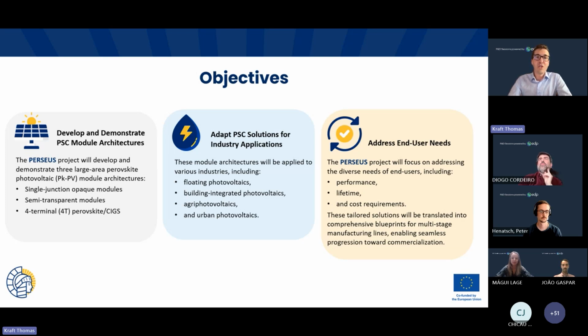One is the single junction opaque module, with a carbon back contact electrode. So basically you're just shining from one side, being illuminated from one side of the PV device. The other is a semi-transparent module in which you can have a bifacial feature, but also the semi-transparency enables this 4-terminal perovskite CIGS architecture.